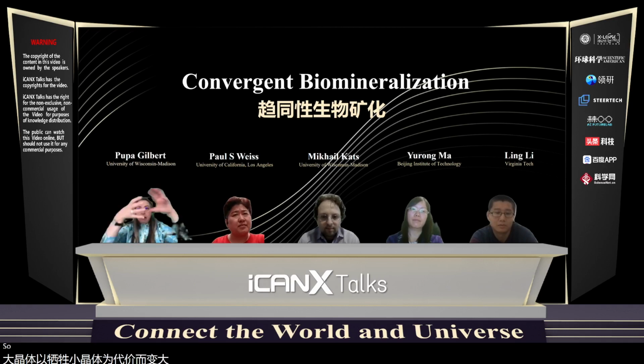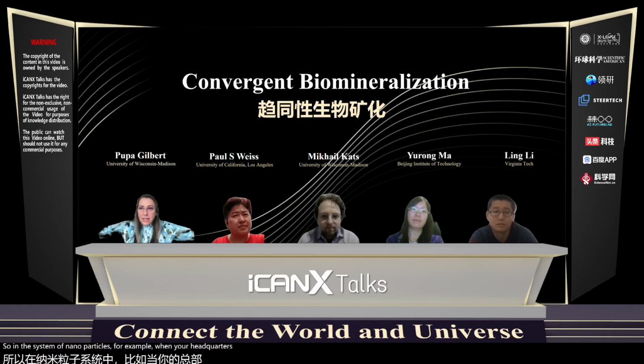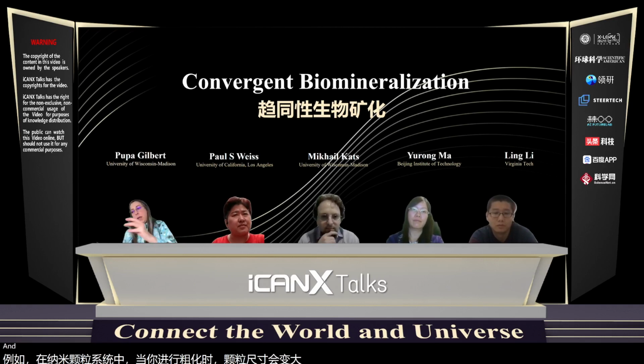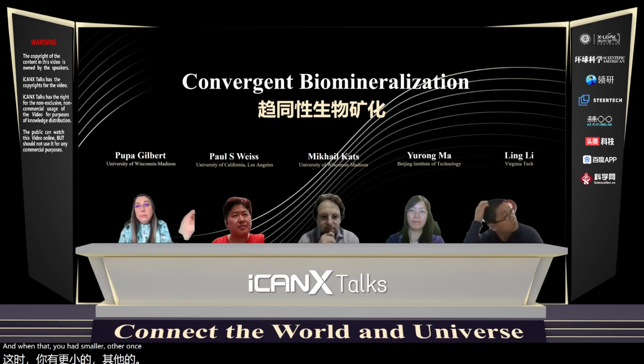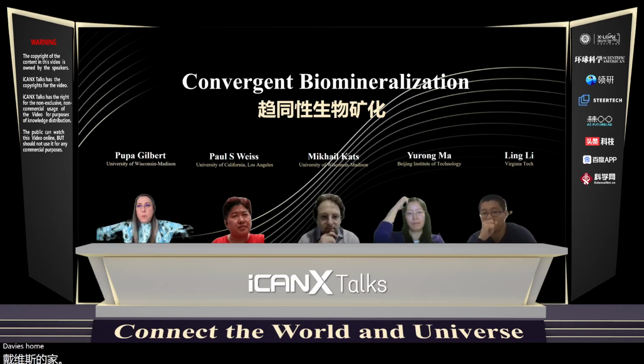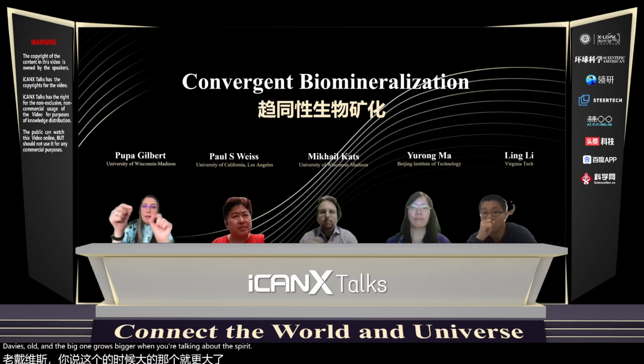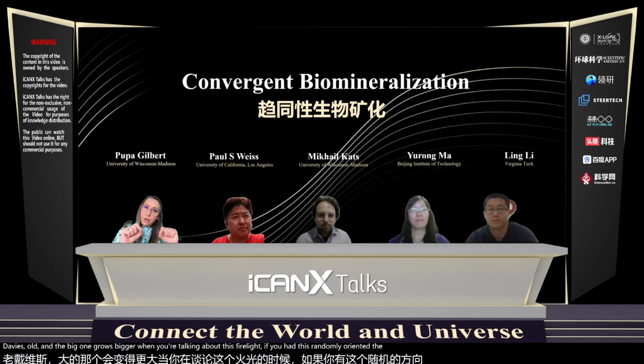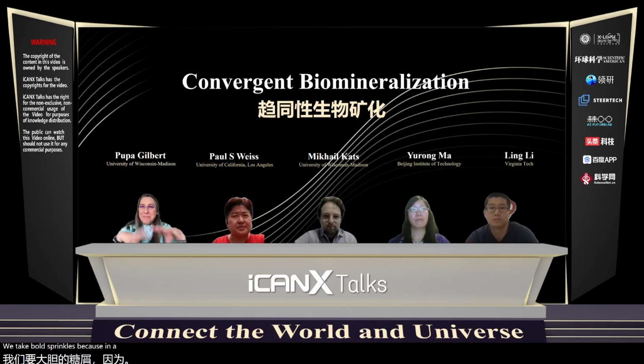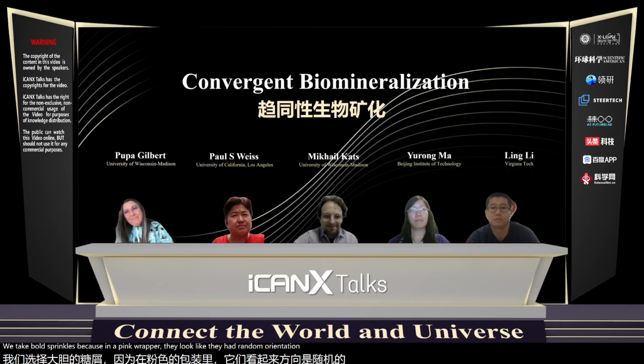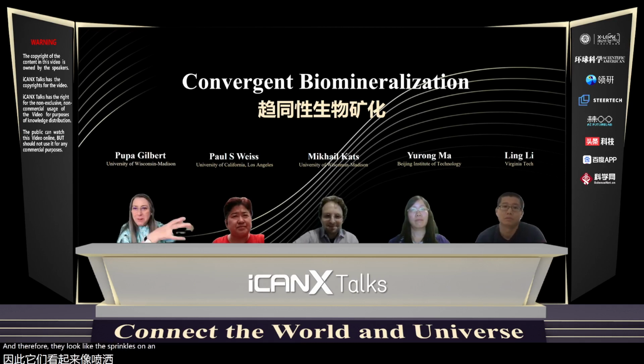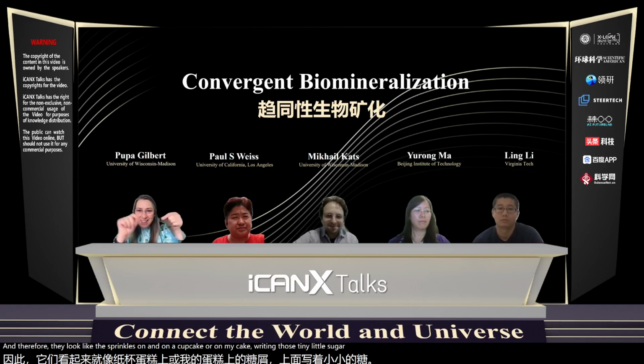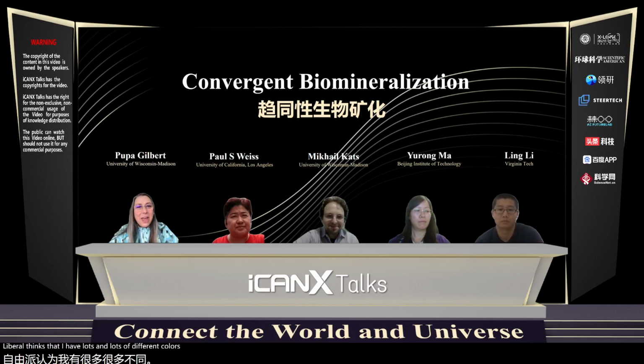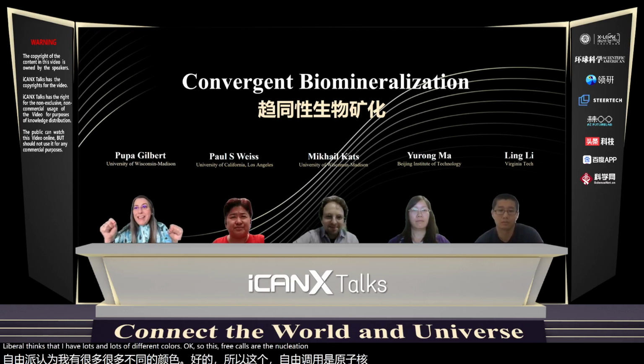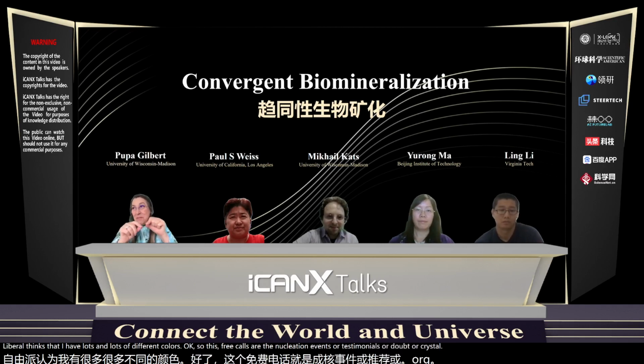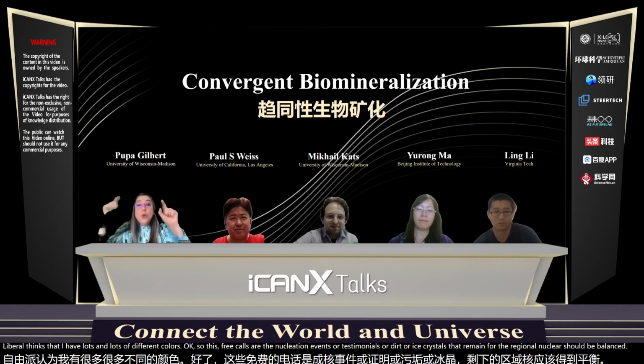So in a system of nanoparticles, for example, when you have coarsening, the grain size gets bigger. And when you have smaller ones, those disappear, they dissolve, and the big one grows bigger. When you're talking about the spherulite, if you had these randomly oriented crystals, which I call sprinkles, because in a PIC map they look like they have random orientations, and therefore look like sprinkles on a cupcake or on a cake, those tiny little sugar things that have lots of different colors. So these sprinkles are the crystals that remain from the original nucleation events. They do not get coarsened.